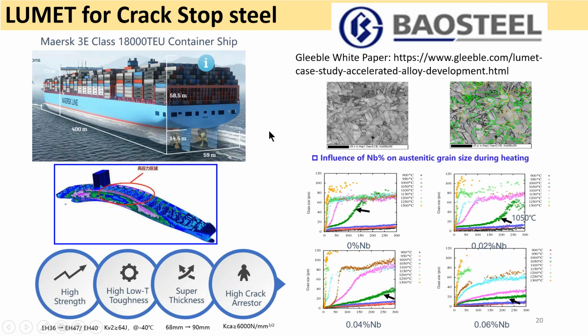Similarly, here, a very important case study which has benefited from these capacities was done at Baosteel in China, in which they were designing a new alloy for a large ship where they would be aiming for very high capacities. And what they have done is the same type of study where they would do isothermal holding in a niobium steel, and they would be able to identify the amount of niobium required to avoid the presence of abnormal grain growth in their temperature of treatment.